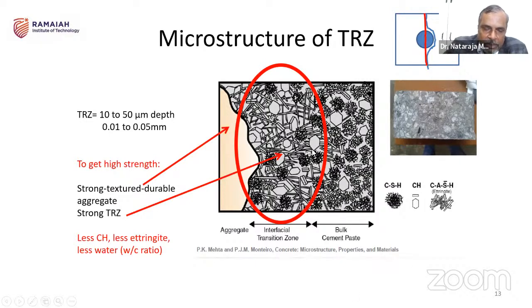It is a sort of schematic diagram only, to get a feel of how this high strength concrete can be really designed. Now this is actually the coarse aggregate, as you can see here. And this is actually the matrix, so the hydrated cement particle. And kindly see whatever the product I just now mentioned: calcium hydroxide, which is in the form of a crystal, calcium silicate hydrate, the one which gives the strength, and of course, the ettringite, which is really not required, which is detrimental to the performance of the concrete. So these are all the materials.